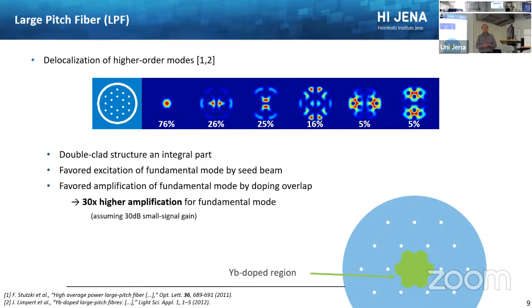And then these numbers at the bottom are basically the overlap of these different modes with the active medium. On the bottom right, we have this green area, the ytterbium doped area. Of course, the modes that are very far outside of this core have a lower overlap, so they are not amplified that much. So even if you start with a mixture of these modes, at the end your fundamental mode basically wins during the amplification process. You regularly get about 30 times higher amplification than for the next higher order mode. So even if you put that into your fiber, at the end you get a nice output beam.